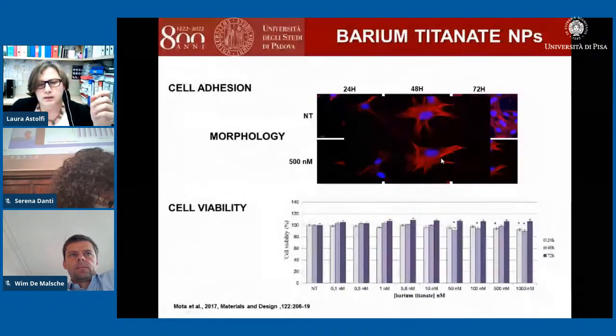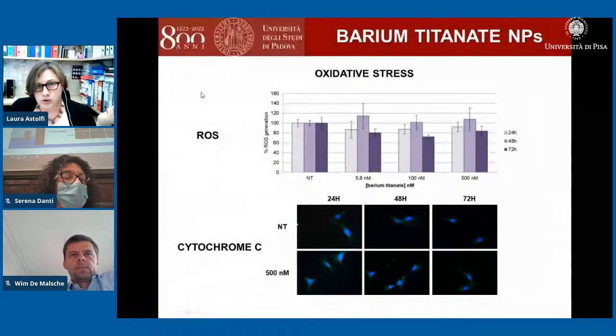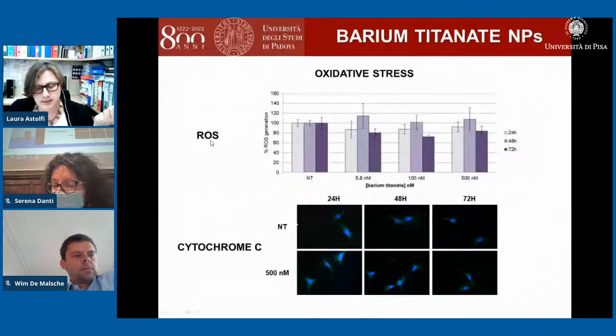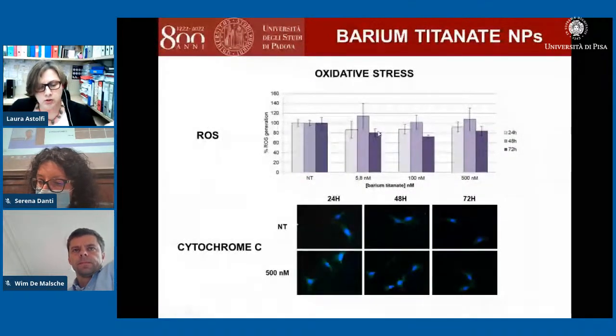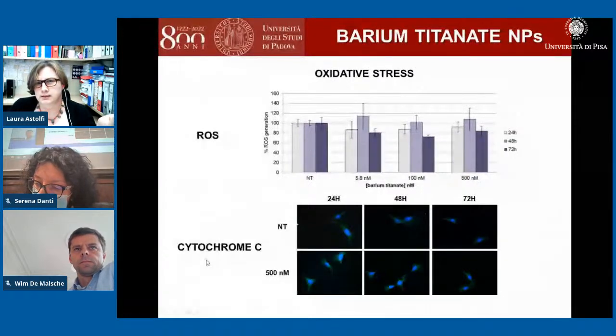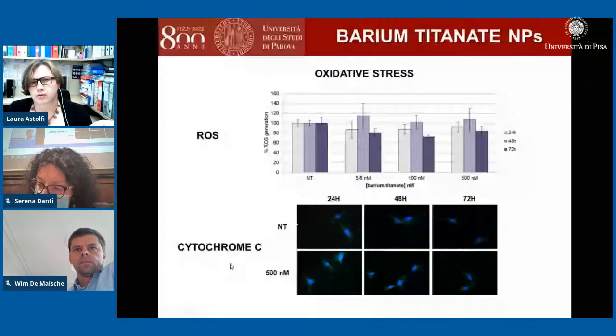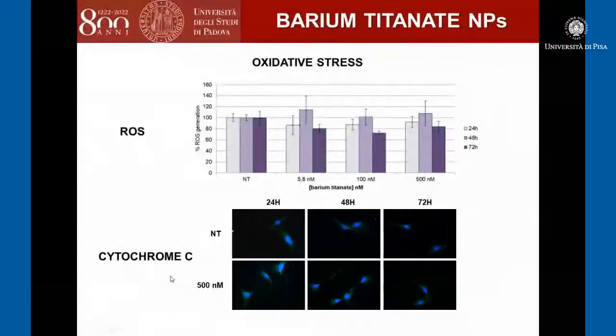To understand more deeply if there is some cell distress, we analyzed the ROS production, and we didn't find oxidative stress. We also analyzed the expression of cytochrome C. Cytochrome C is a marker of cell distress. When the cells are not in healthy condition, the membrane of the mitochondria is damaged, and the cytochrome C goes outside of the mitochondria into the cytosol. As we can see, after 72 hours at the highest amount of nanoparticles tested, we have spotty expression of the cytochrome C, so it stays inside the mitochondria. So again, there is no distress because they are in healthy condition.